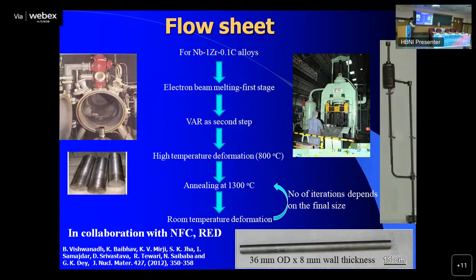This is again a collaborative work between Nuclear Fuel Complex, Reactor Engineering Division, who are the users, and these were the fabricators and the materials group. And that led to the fabrication of these tubes of niobium 1 zirconium 0.1 carbon alloy. And using these tubes, this loop was made, and I was told by Dr. Bijayan, this loop uses lead bismuth as the coolant, for testing this high temperature material. And this loop holds the world record for the highest temperature loop, 1000 degrees centigrade. That's what I was told by the user. That's Dr. Bijayan's group in those days.